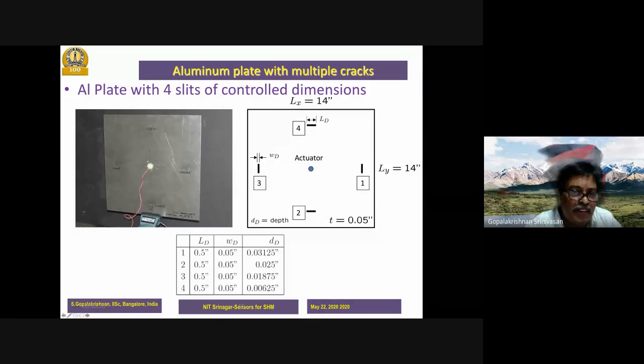Essentially, we have a very large aluminum plate. We made different cuts here. You see 0.03, 0.00625, 0.01, 0.025. And we chose to monitor only small regions close to this crack to see what this vibrometer gives. And this is the length of the crack, you can see.